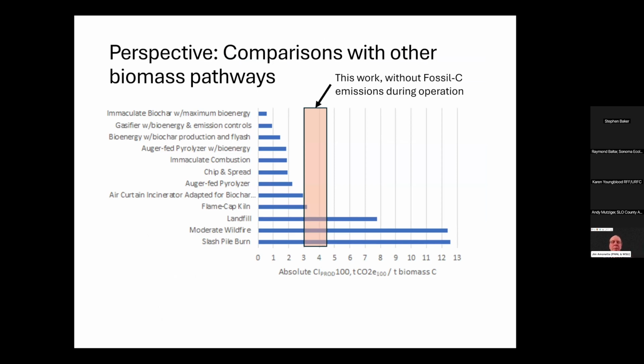Basically, this reddish rectangle gives you an idea of the range. This is subtracting those fossil carbon emissions that occurred during the operation for the field. Rather than just apply them across the board to everybody, if you take them out, they average about 0.5 tons of CO2e. So this whole thing is about 0.5 lower than those numbers I showed you in the previous slide. But the main takeaway is that if you look at the typical numbers, like Steve was referring to, for a wildfire or a slash pile burn, we're way down below, about a third of those. It's quite a bit lower.